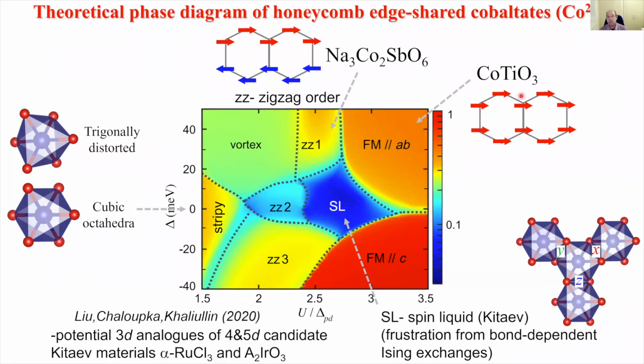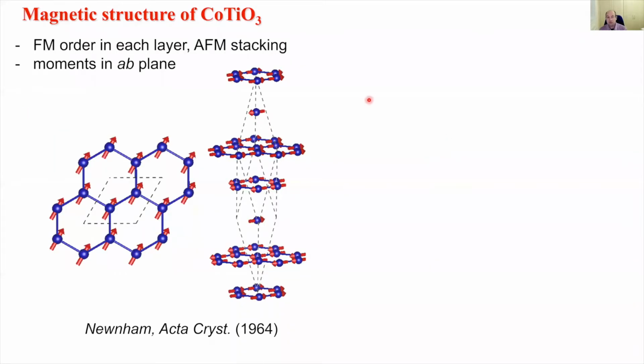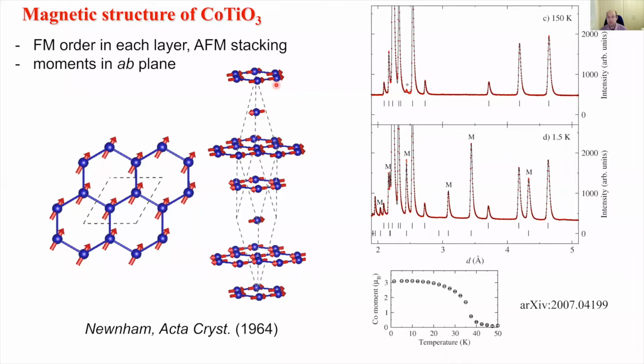So I'm going to focus today on this material cobalt titanate, which is in this ferromagnetic part of the phase diagram, with spins in the AB plane. So this material has been known for some time to have a ferromagnetic order with spins in the plane, and also antiferromagnetic stacking along the vertical direction. And we've recently revisited that with powder neutron measurements and verified this model for the magnetic structure, and also obtained the magnitude of the ordered moment in the ground state. So here is a comparison between powder measurements at high temperature and at low temperature. There's a lot of new magnetic peaks associated with this type of magnetic ordering. And I might come back later in the talk to explain how this magnitude of the moment gives us insight into the spin and orbital mixture of the magnetic moments in the ground state.